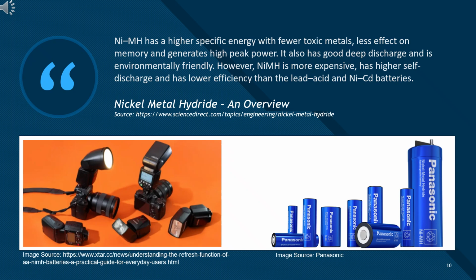Nickel-Metal Hydride: An Overview. Let's take a quick pause here and look at this summary from "Nickel-Metal Hydride: An Overview" on ScienceDirect. It nicely captures the key trade-offs of NiMH batteries. They offer higher specific energy, fewer toxic materials, less memory effect, and good deep discharge performance, all with strong environmental benefits. However, they also come with some limitations, such as higher cost, greater self-discharge, and lower efficiency compared to lead-acid or NiCd batteries.